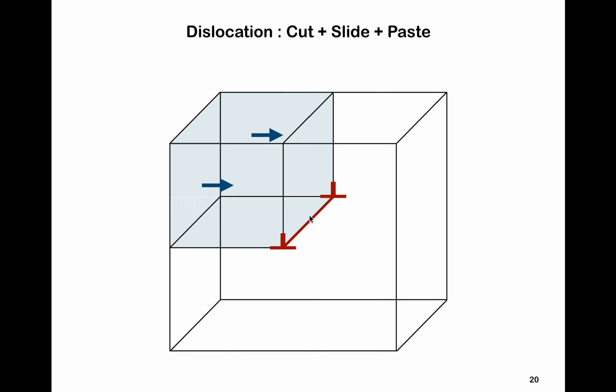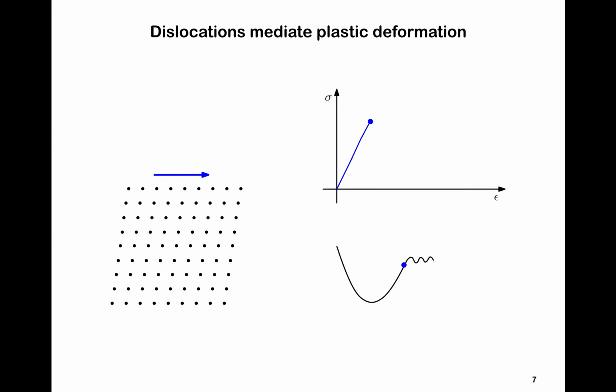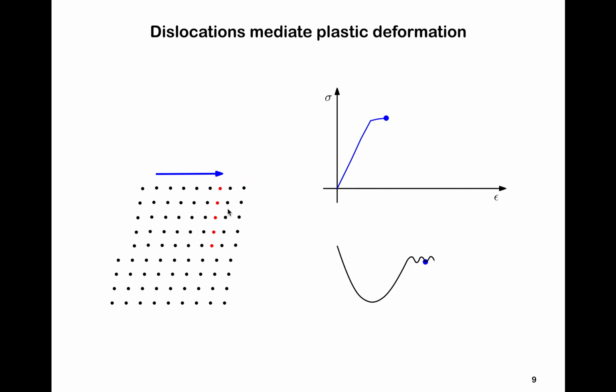Remember also that the way we got this dislocation was by pushing or shearing the left side of the crystal across the slip plane towards the right. If I go back to this picture, and you focus on the top half of the left hand side, you see that the left part is compressed, but the right half remains uncompressed. So ahead of the dislocation there is a compression, behind the dislocation there is no compression, and the same thing holds true here. Now you see there is no compression here, but these parts are compressed.